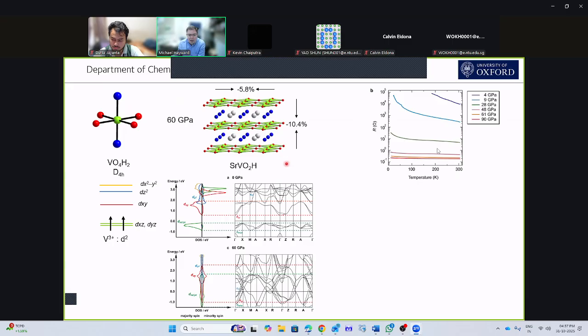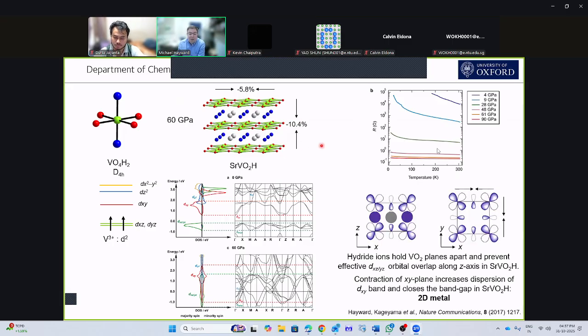But the key point is that this large contraction in the c direction isn't what makes the system metallic. While the xz and yz orbitals are pointing at each other in that direction, this hydride ion sits with its s orbital between them and stops them mixing. So even though there's a large contraction in this direction, this doesn't close the band gap.